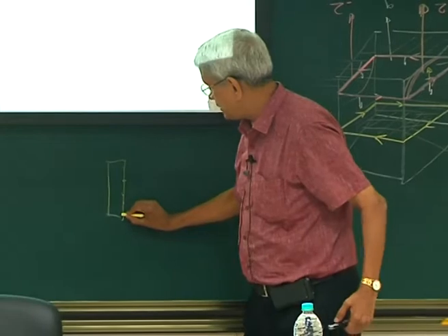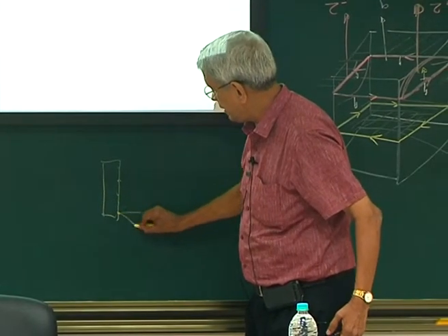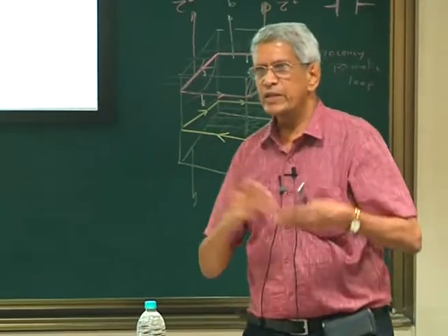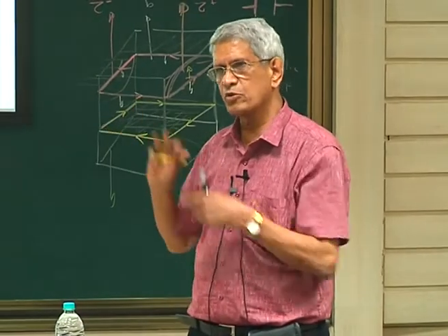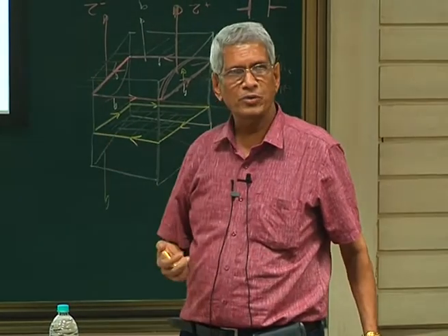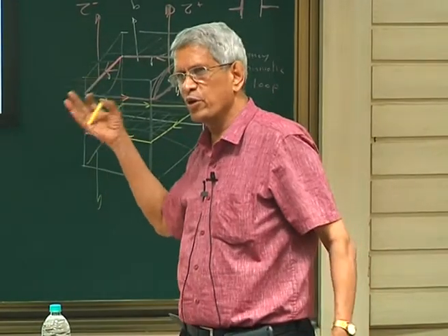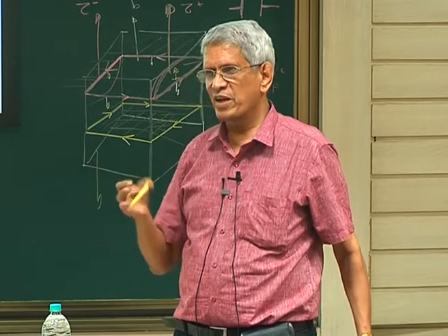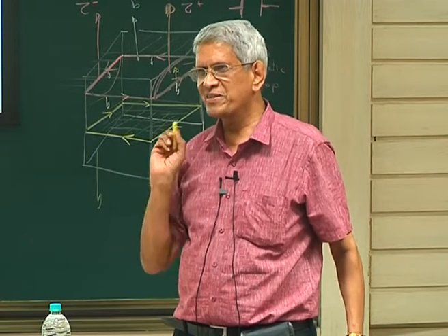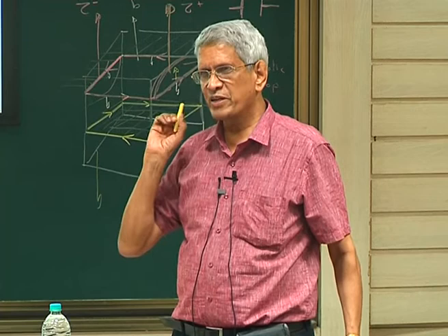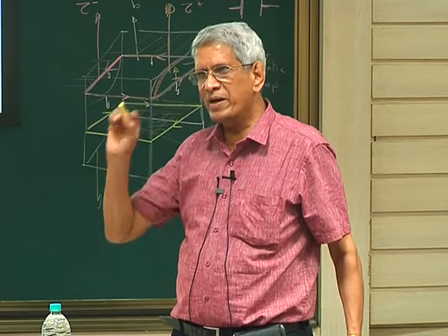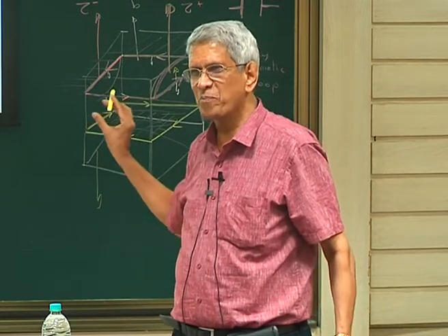If I look at the radiation scattered in a particular direction from various points of that sample, and they join together, suppose we can make lenses to join them, or they join together at infinity, what is the total amplitude, provided the probe is coherent? Constructive interference is when they all add together. That's what diffraction is about: rays scattered from different points on the sample, but in the same direction, and the net amplitude they have.